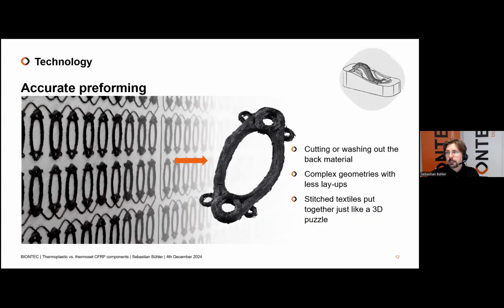In some cases, it's necessary that we have to get rid of the back material. And in some cases, it's necessary that, for example, a glass fabric has to stay in the part. Then, of course, we have a bit more cutting waste. But the substrate is very, very thin, about 40 grams per square meter. So this is a very lightweight substrate. You can wash it out, you can burn it out. In former times, the textile industries also used acetone, but because of recycling and sustainability, this is not the perfect way for us.